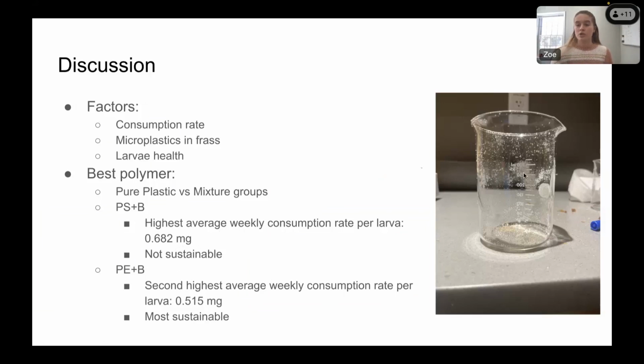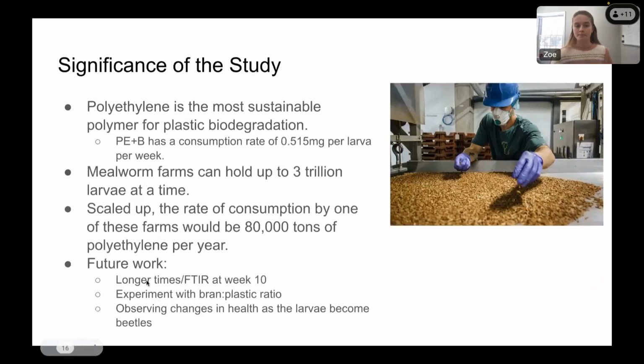As you can see in this picture right here, when the worms were consuming the polystyrene, they were creating microplastics, which goes against what this project was for, which was to make plastic degradation more sustainable. So polyethylene and bran had the second highest consumption rate of 0.515 milligrams per larva per week, and it was the most sustainable, a lot more sustainable as compared to the polystyrene, because there was none of this creation of microplastics, and there was a better digestion, as we saw in the FTIR.